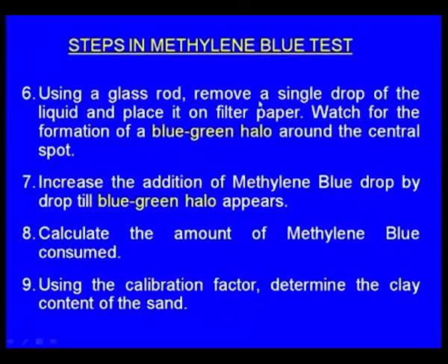Using a glass rod, remove a single drop of the liquid and place it on a filter paper. Watch for the formation of a blue green halo around the central spot. This is the indication that the active clay is exhausted and methylene blue is dominating.